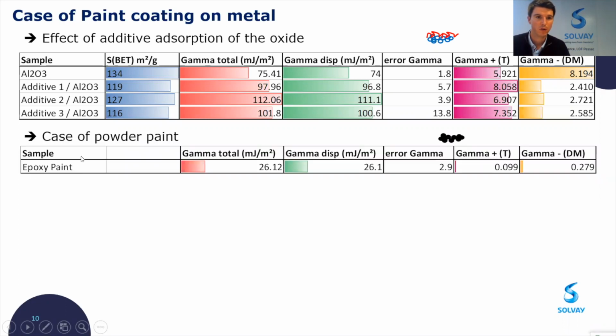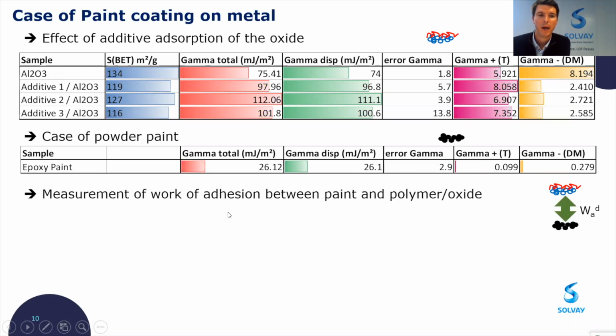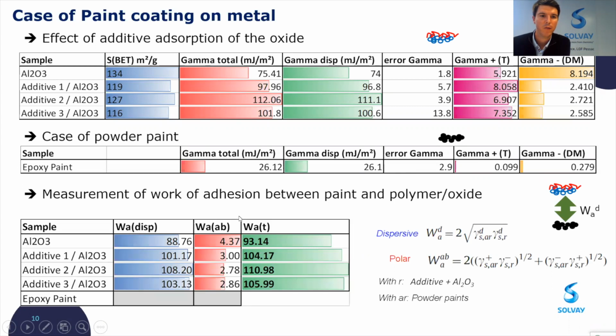We have measured also the surface energy and gamma plus and gamma minus for the epoxy paint. As you can see here, the values are lower compared to aluminum oxide. And we can estimate with these values here in the tables the work of adhesion and compare different additives.